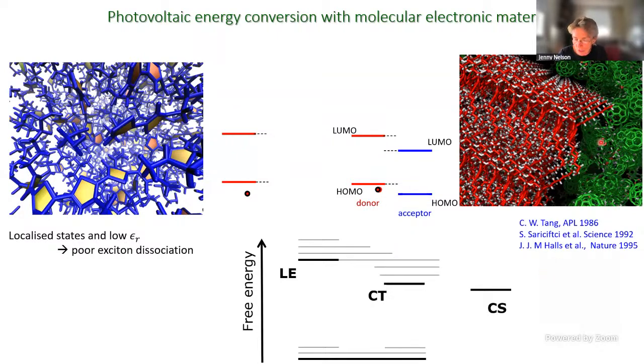And so what happens now if we come in with a photon? We will excite an electron from the ground state to an excited state. And then rather than that electron falling back down again, it's now able to take part in charge transfer. And so the electron could be transferred from one material to the other. For example, if the photon was absorbed in this polythiophene here, then from the excited state, the electron could transfer to the other material, which in this case is a fullerene. And then we would have hole here and electron here, and we would have a charge transfer complex sitting across the heterojunction. So this state is more stable.